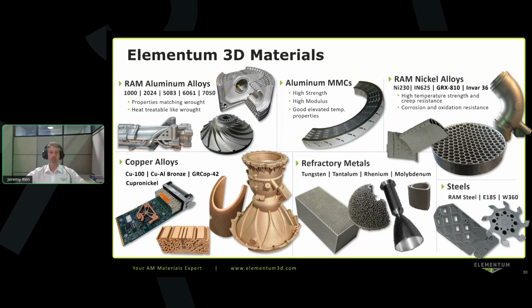We have copper alloys that we've been working with. We have a commercially pure high conductivity copper. We have a copper RAM alloy that we're developing that we plan to release here in the not too distant future with a couple versions of that. One for very high conductivity with excellent printability. Copper is challenging to print to full density because of the reflectivity of the material as well as high conductivity. But this RAM alloy can solve some of those problems, make for a very printable high conductivity material.